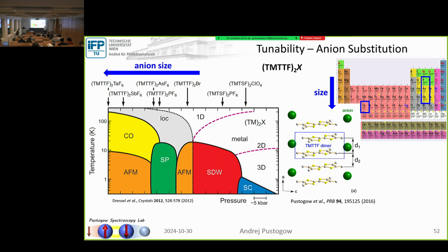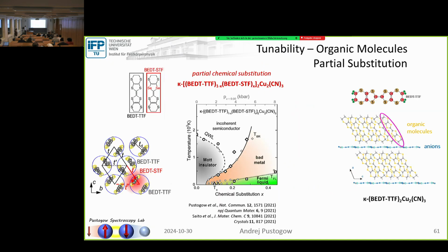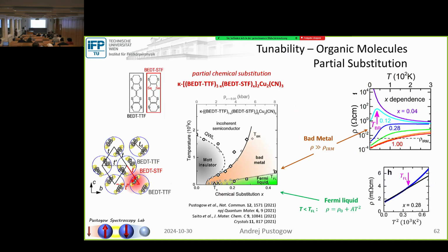First of all, thank you for the talk. I just have a technical question for the pressure measurement you did. I guess you use a diamond anvil cell for applying pressure to the sample? Actually, no. I mean, people nowadays do this, yes. But diamond anvil cells, they typically reach pressures of order several GPa. I mean, 1 GPa is 10 kilobar. And these organic compounds, you can get this phase transition here already at about 1 kilobar or even less.